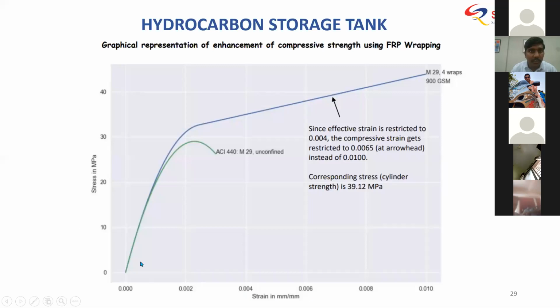Graph of stress versus strain of wrapped, FRP strengthened concrete. This is one of the programs that I have done in Python to show the behavior of concrete in FRP wrapped and unwrapped condition. This is the bare concrete, the green curve that you're seeing. That is M29. It barely touches the M30 line, so M29 is the maximum strength of the existing concrete. And then after FRP wrapping, this blue curve is the stress strain performance curve, wherein you have to limit, as discussed earlier, the strain to 0.0065 as per the calculation, and at that point you are getting around 39 MPa, and that was found sufficient for this particular project.